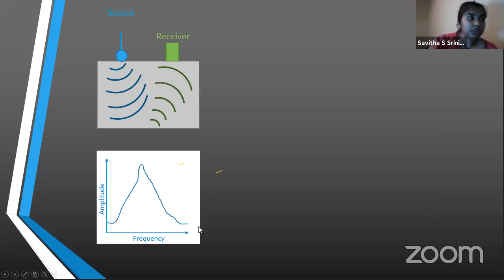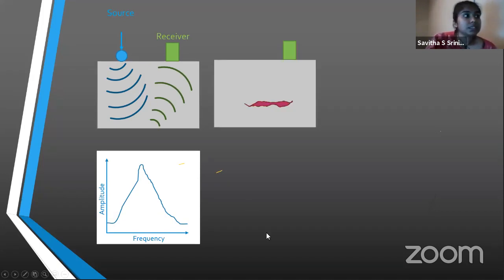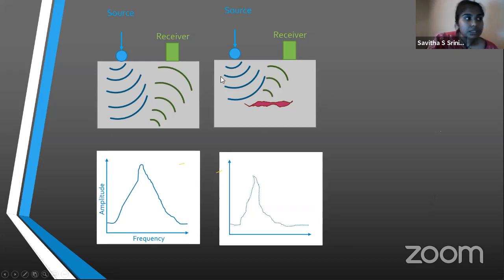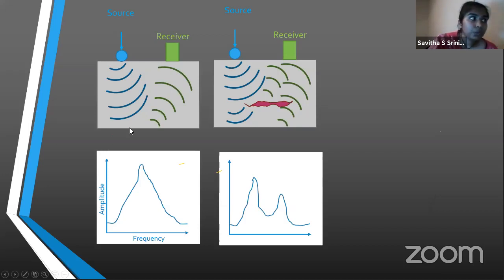The impact echo method essentially involves a source that will generate a pulse through your sample and you receive it. So what you'll get is a graph that's something similar to this. Now, if you have a flaw in the system, when you have your source, it will generate a pulse, which will hit the receiver, and you get a graph like this. But there is also some leakage of the source pulse that comes down, which will hit the end of your specimen and go back. So you get this curve as well. You will get a modulated curve that looks like this, which is smaller than what you would expect for a system that does not have any flaws.